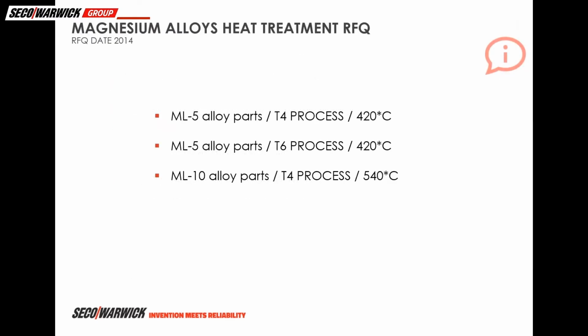In 2014, SECO WARWICK was requested to quote the line for solution heat treatment and aging of magnesium parts for aviation industry. The subject of the inquiry was magnesium alloy series ML5 and ML10. The customer needed an equipment for T4 and T6 processes at 420 and 540 degrees centigrade, respectively. After an initial specification analysis, a draw bottom furnace was selected.